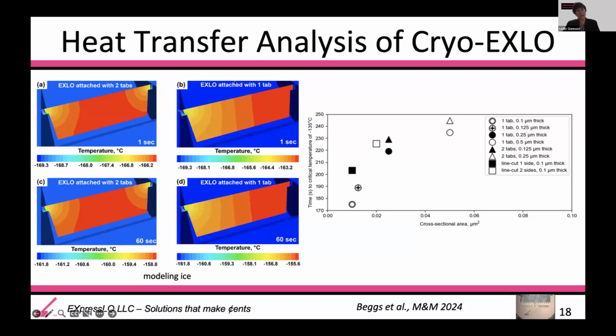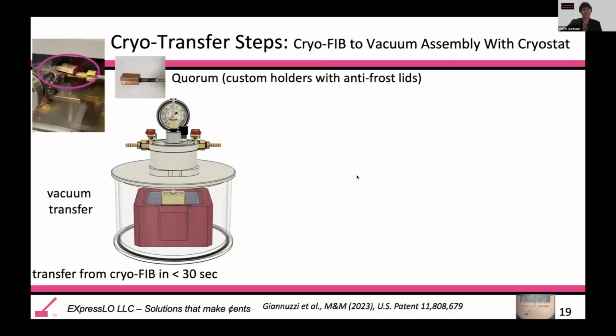But what this shows is that as long as the specimen remains touching any part of the trench wall, it will remain vitreous via conduction. And so this shows that the FIB method itself in producing a cryo ex situ lift out specimen will in fact theoretically work.